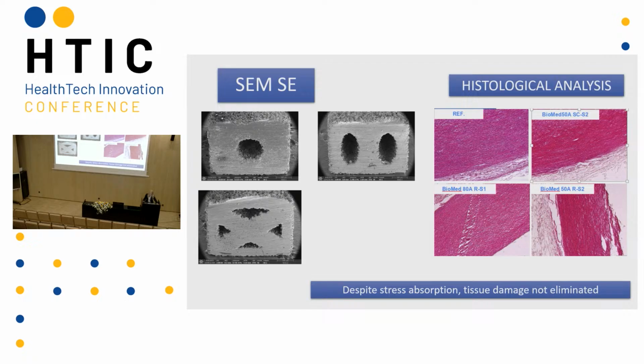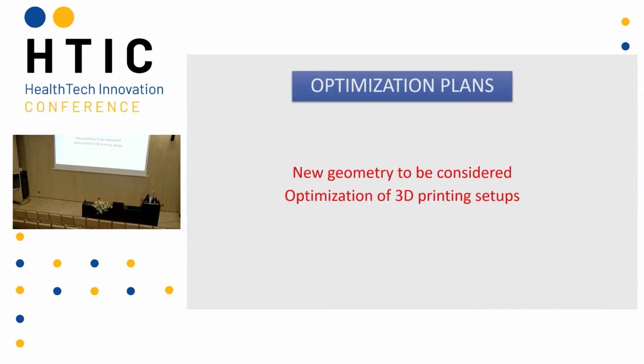As for the histological analysis, despite the stress absorption, tissue damage was not eliminated. Here we are seeing reduced tissue damage from the level mild to moderate. However, we have the ambition to eliminate the tissue damage completely. So now we are working on the new geometry of the metamaterials, just to improve the overload protection of the tissues, and we also want to optimize the 3D printing setups.